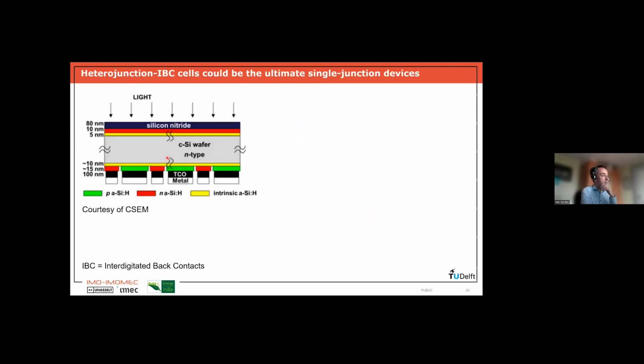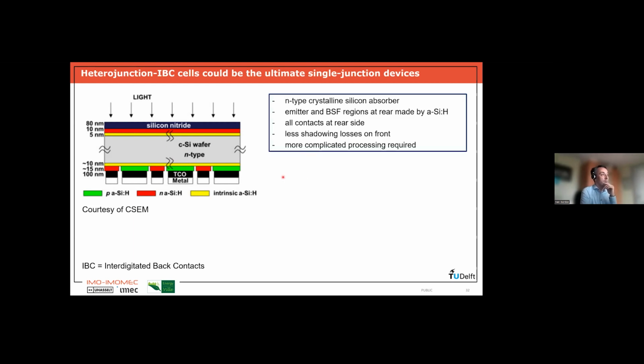And here I give the example. There are different examples. I give one example of a back junction cell, which is a heterojunction IBC cell. The IBC stands for interdigitated back contacts. So in this case, we have an N-type silicon wafer. We have some front side passivation, but there is no metal contact this time at the front. All the metal contacts, the negative and the positive polarity, they're all at the rear. And in this case, it's a heterojunction cell. So again, we have these very thin amorphous silicon layers to passivate the front and the rear. So the emitter and the back surface field regions are at the rear, in this case made by amorphous silicon.